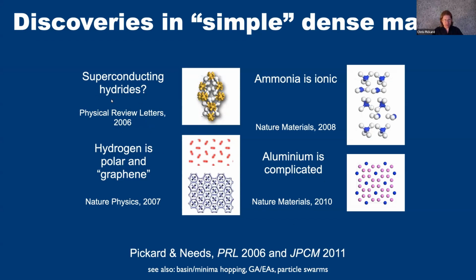The first, when we published the methodology of random structure searching, was looking for hydride-based superconductors. It had been proposed by Neil Ashcroft that if you combined hydrogen with some other element, you might be able to trick hydrogen into becoming metallic at lower pressures, and that might lead to a high temperature superconductor. There's a whole story behind that, which I'll dip into a little bit later on. But there are other works, such as determining good low energy candidates for pure hydrogen at high pressure. We found that when we squeezed ammonia above about 50 gigapascals, it spontaneously ionized and became ammonium amide.